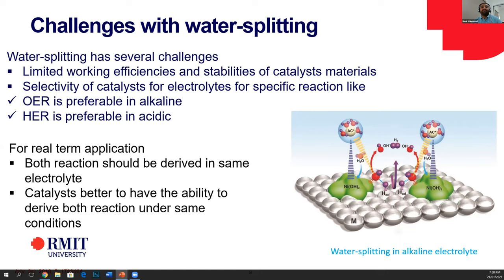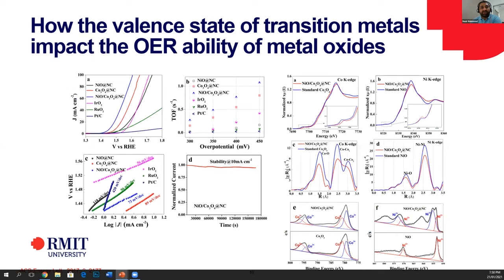I will just highlight a few examples from my group. We tried to make some catalysts. Metal oxides are very good for doing OER. So we developed some metal oxides, and we found that mixed transition metal oxides are very good. Like we mixed nickel oxide with cobalt oxide. Simple mixing didn't give us very good results. What we found is that if we have nickel oxide and cobalt oxide, both existing as individual entities but in close proximity to each other, they impact each other's oxidation states. When they are close to each other, we get a higher oxidation state.